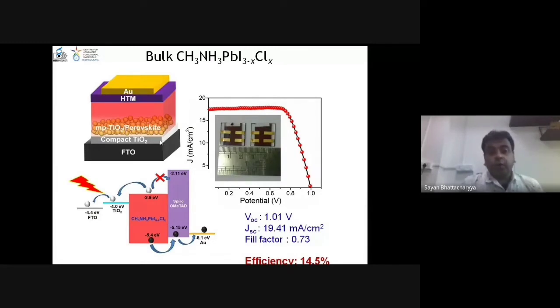When I talk about solar cells, this is the way we make it. You have a conducting fluorine doped tin oxide glass, which is a conducting, transparent glass. You need an n-type semiconductor like compact TiO2. You have the mesoporous TiO2, which has a lot of pores. When we put the bulk system, this is not a nano system, this is the bulk system. We can also mix in the nano here. This is the absorber, the perovskite, methyl ammonium lead iodide, with some chloride also. After that, this is the electron transporting layer, which transports the electrons this side. This is the hole transporting material. Various hole transporting materials are very expensive. Sometimes people are making new ones, and you need to have the top contact, which is gold.